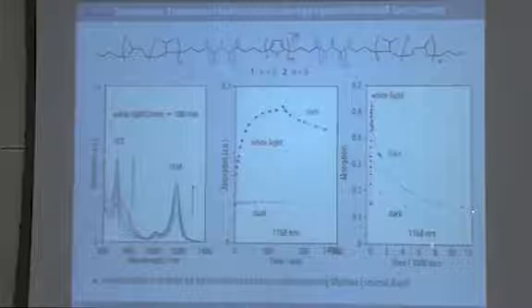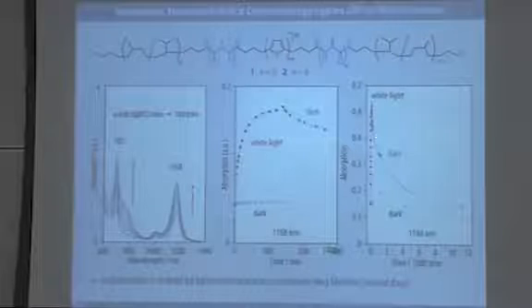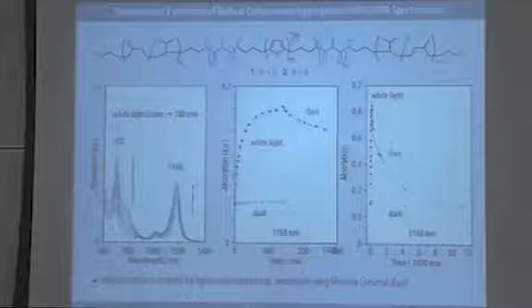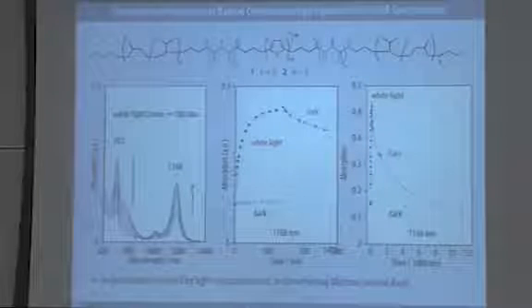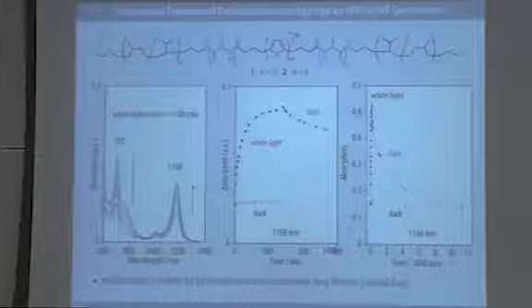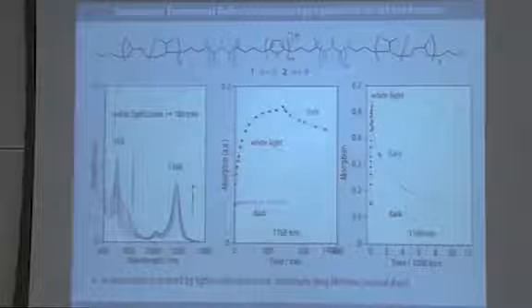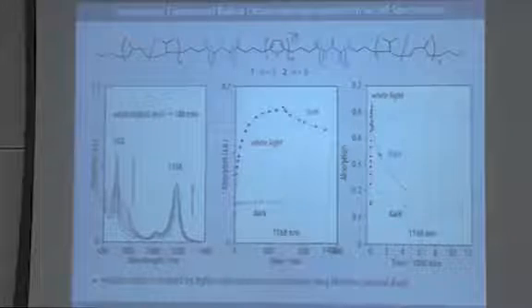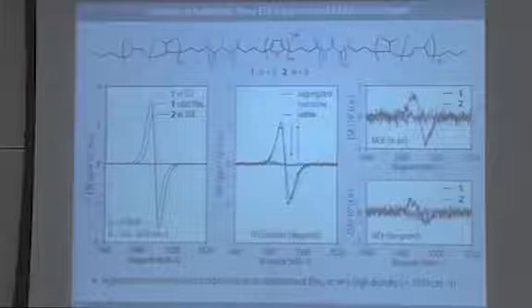the intensity of the signals decays again, but as you can see here, the decay is actually very slow. This is a time frame on the order of 1 week until it finally returns to its final state. So, I think we can say we have a surprisingly long-lived radical cationic species that only, probably due to some follow-up chemistry, then slowly disappears. Sure enough, if it's a radical cation, it should also show an ESR signal, and it does.